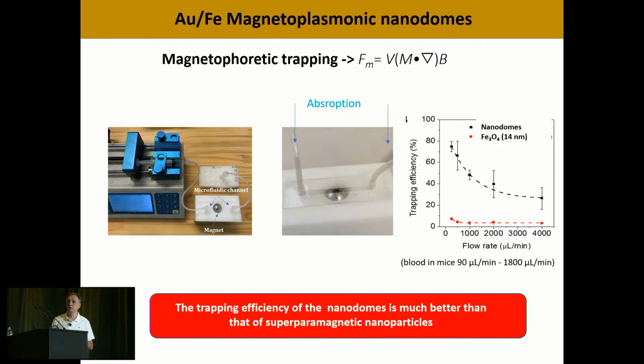We did the same experiment using 14 nanometer iron oxide nanoparticles. And you see here that even at very low speeds, our trapping efficiency in this case is less than 10%. So this demonstrates that our nanodomes are much more efficient to manipulate using magnetic fields than iron oxide nanoparticles. Because, as I said before, the total moment of our nanodomes is about 500 times stronger than the total moment of an iron oxide nanoparticle.